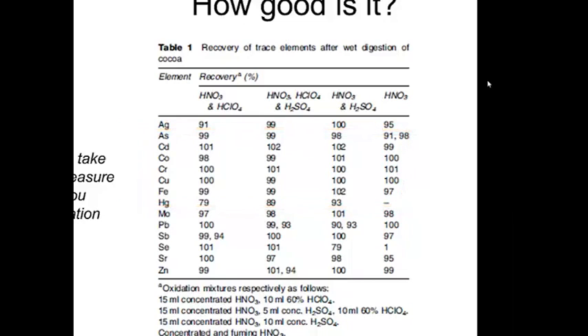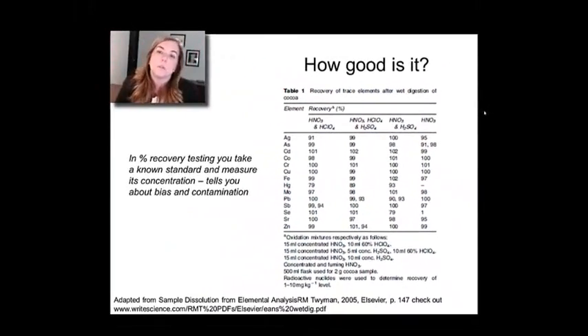And this table actually reports that for the wet digestion of chocolate, which is our next case study, but I included it here. And what you can see is that most of these elements, depending on the acid, are recovered pretty well. Silver maybe a little bit less, but I want you to look at the table and tell me which elements maybe didn't work so well. You can see, for example, actually lead had some really low numbers there. Another one you'll notice is mercury, particularly with nitric acid. And mercury is famous for being a volatile metal. And so what that means is when you're doing mercury analysis, if you basically heat it at all, it can come off as a vapor, which is bad for your analysis and also bad for you.